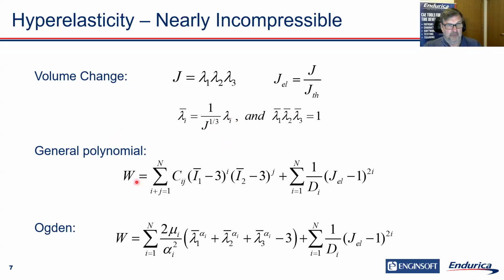There's a couple of forms here for W with this nearly incompressible form. Here's a general polynomial. You can see if I just take the first term, I is equal to 1, J is equal to 0, I get C10 times I1 bar minus 3 to the first power, and that's the Neo-Hookean law we saw previously. And you can take as many of these terms as you want. You'll just need to be careful in characterizing the coefficients that you maintain the response that you want. So this is the volume conserving portion.